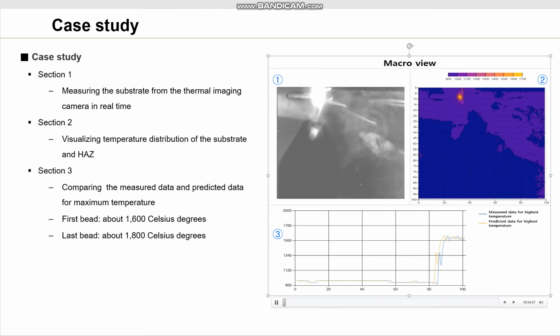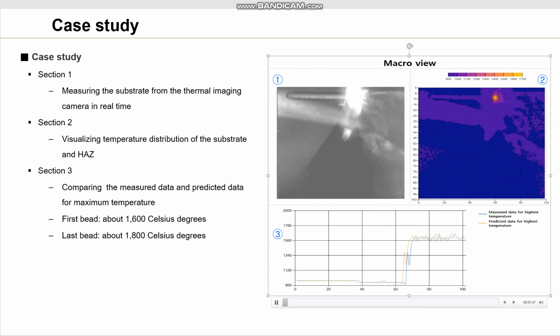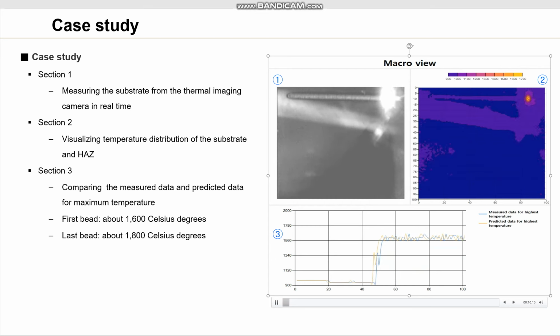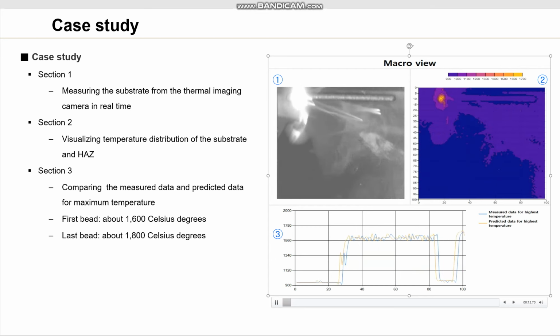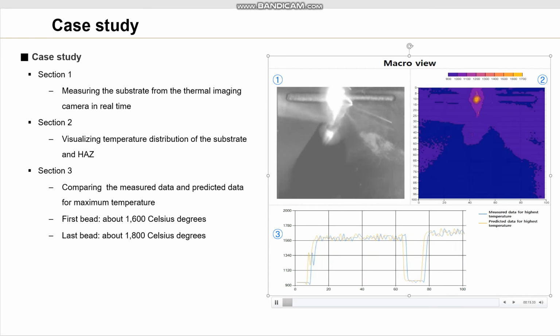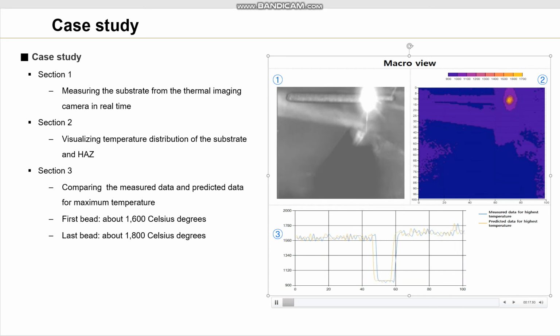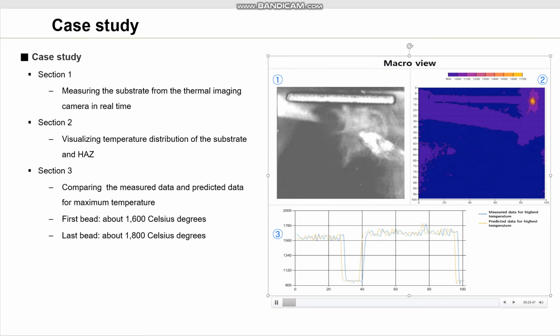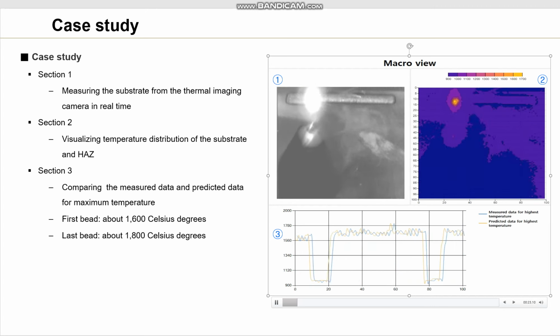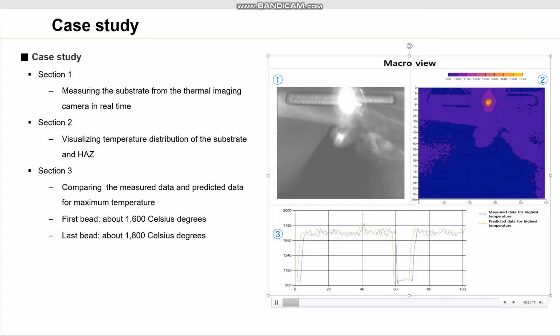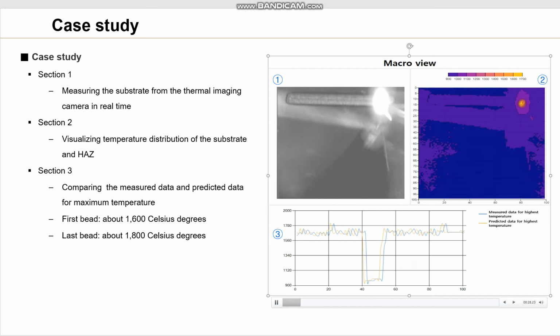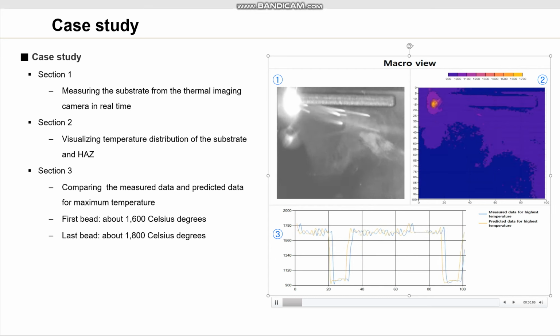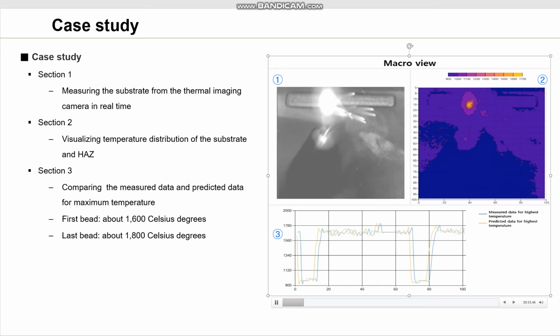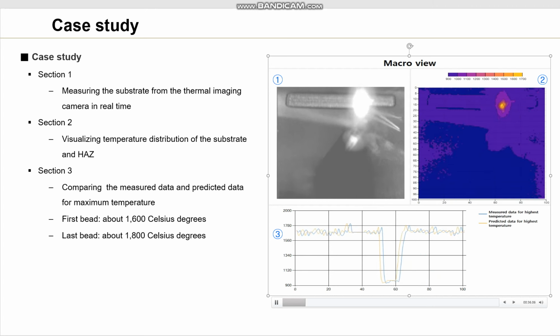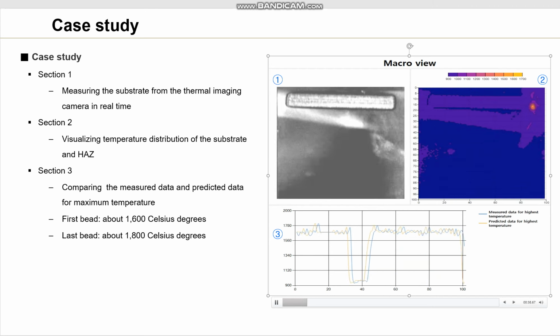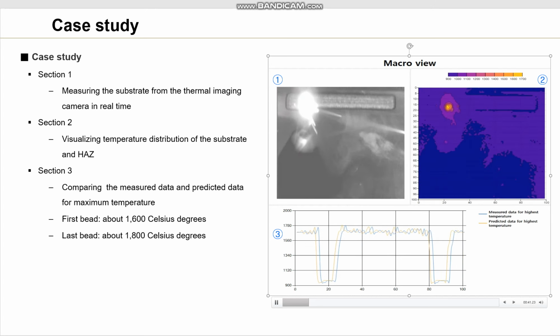In this slide, you can see a sample video of the thermal profile prediction model developed in this study. The screen is divided into 3 sections. In the first section, during the laser cladding process, a laser beam is irradiated to the surface of the substrate, and then the alloy layer is formed between the substrate and the powder. In the second section, you can check the temperature distribution of the substrate and the heat affected zone measured from a thermal imaging camera in real time.